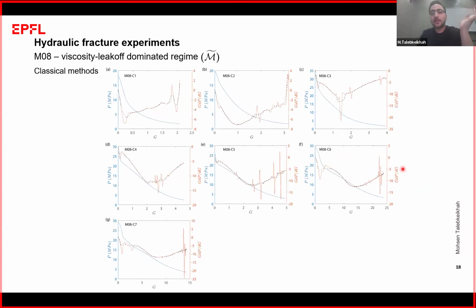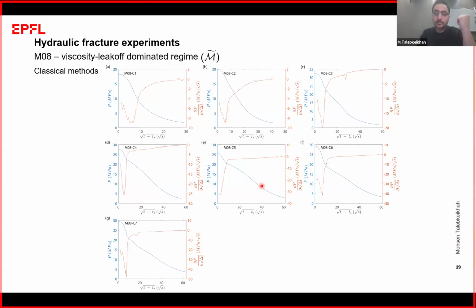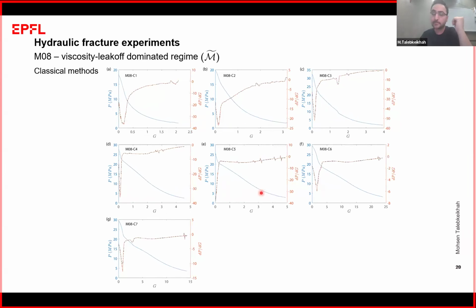Also, I checked the classical methods. Here you can see the tangent method. However, I don't like the peaking with the tangent method because it will give us a value that is unexpected. And also the other method, pressure versus square root of delta T, the value that it gives us is not really expected. But the compliance method, however, where we have a high leak-off and permeability is high, is consistent with the value that we pick with the stiffness figure.